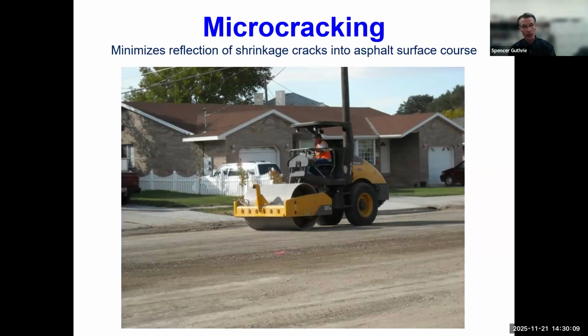The vibrator is on full amplitude, so this is bouncing, to induce a lot of energy into that cement treated base. And we just walk it along, kind of a fast walking speed, until we've achieved the cracking pattern. Then we stop. Very important to stop before we go too far or we damage the cement treated base.